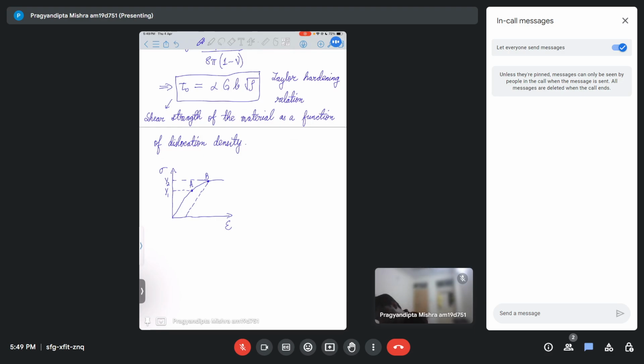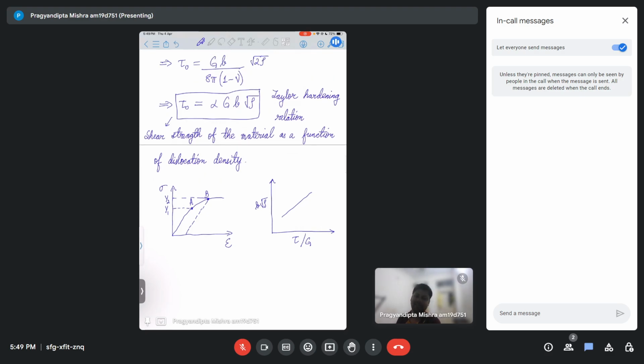Essentially, what people have done is they have done experiments and plotted this b root rho, the root of dislocation density times Burgers vector, versus tau normalized with G. What they have seen is that they got a straight line for this. So this also proves that this Taylor hardening relation is actually correct.